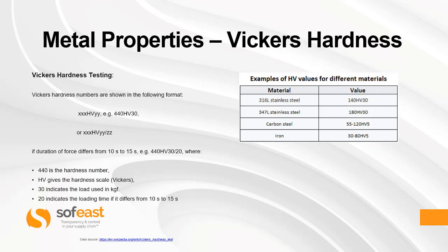So some typical examples of the materials with the Vickers hardness test results are here. So we can see the 316L stainless steel has 140 HV30. The 347L stainless steel is slightly harder, which is 180 Vickers 30. Carbon steel, which is between 55 and 120. And iron, which ranges between 30 and 80.